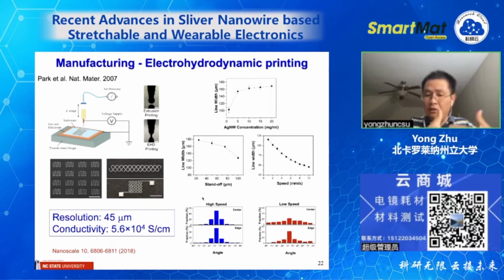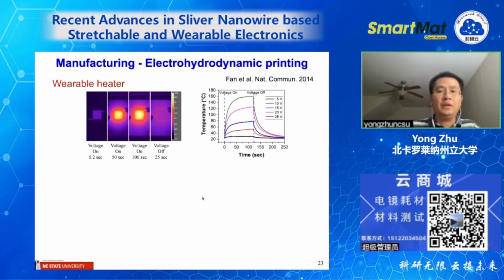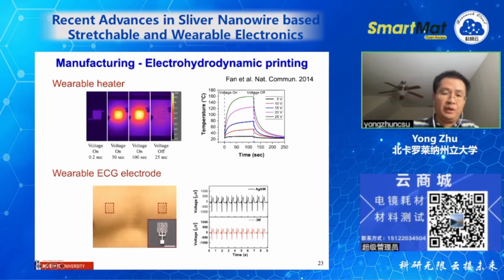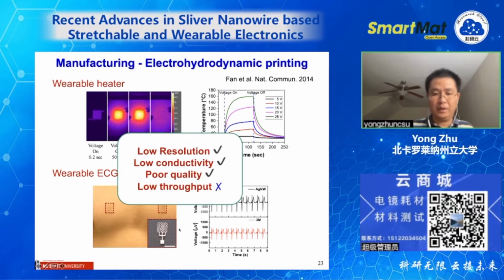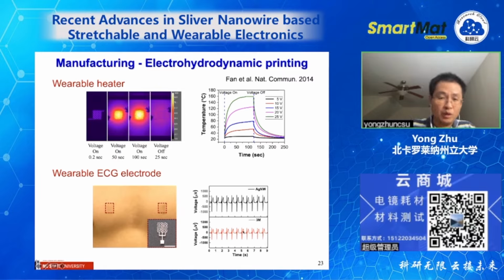So the printing speed can help us adjust the alignment. The alignment is also important, right? The structure can have important implications for the properties. As demonstrations, we printed some rather complicated features. This is a fractal pattern. We use the fractal pattern as a heater, which can cover a relatively large area and still provide uniform heating. We also printed an EKG electrode. In this case, you can see it's transparent, or at least semi-transparent, because we don't have a solid structure, just this fractal pattern. We compared the 3M commercial electrode with our silver nanowire electrode, and the signal quality is pretty much very similar.